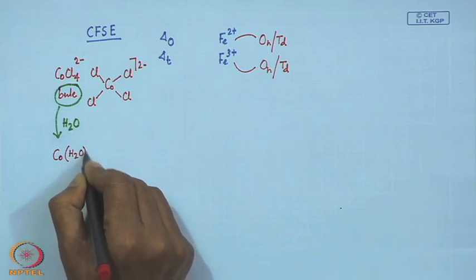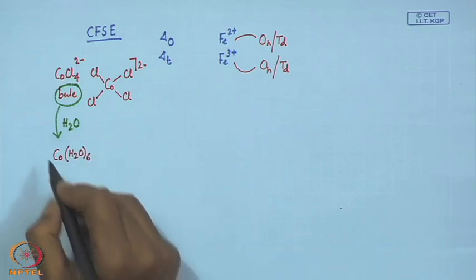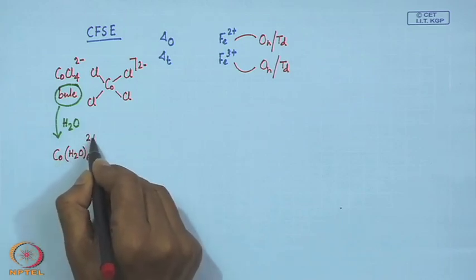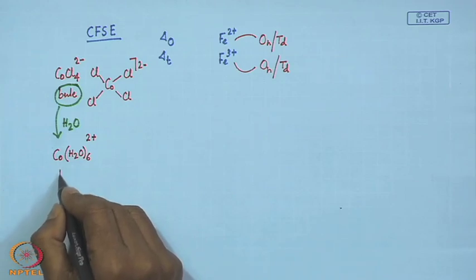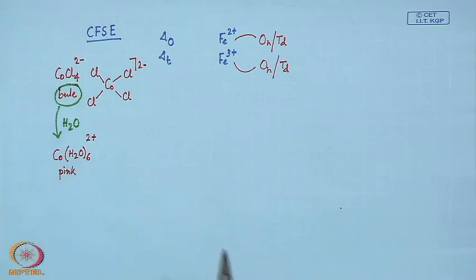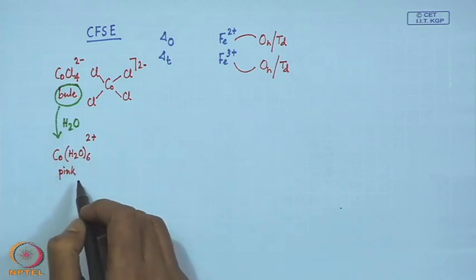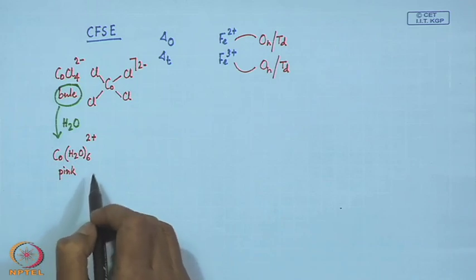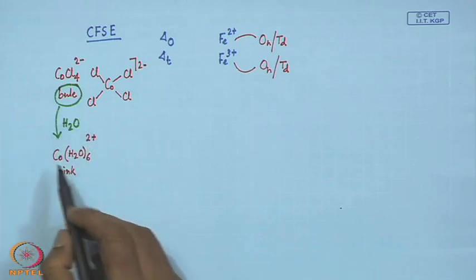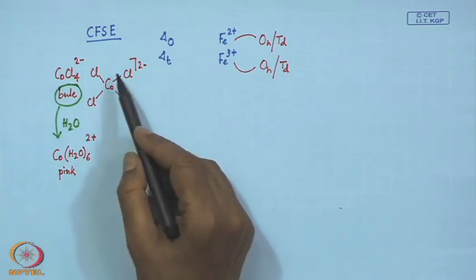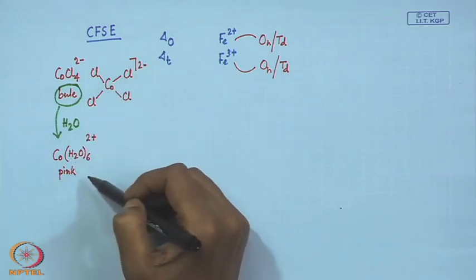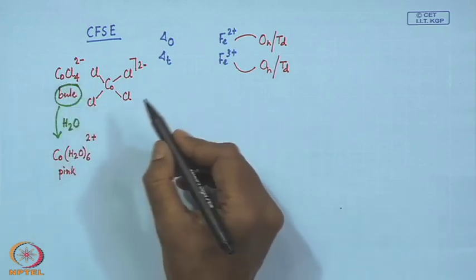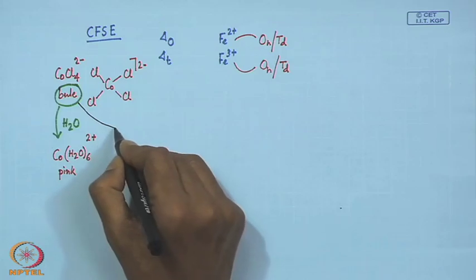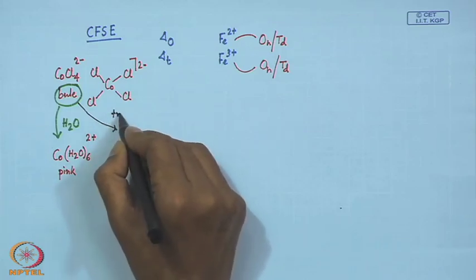cobalt hexaaqua, which is 2+, and the color also changes from blue to pink. So this change from the chloride environment to the water environment, that is the oxygen environment, changes the corresponding values of the CFSE, and in the octahedral environment this arrangement is stabilized. So once we change the environment, we get a corresponding color change. So this tetrachlorocobaltate can be trapped.